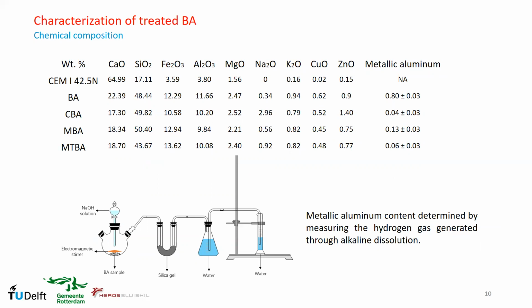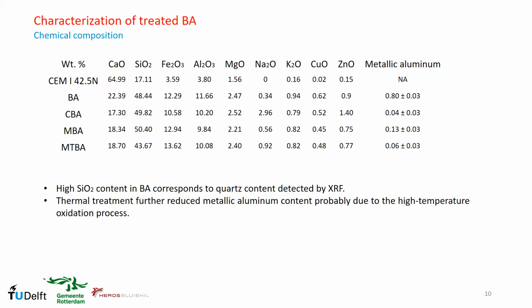Next, the chemical composition of the treated bottom ash by XRF. Here we see that in all bottom ash samples, the calcium oxide content is much lower than in Portland cement, while the silicon oxide is much higher in bottom ash, which corresponds to the quartz peaks detected by XRD. The metallic aluminum content is determined by measuring the hydrogen gas generated through alkaline dissolution with the setup illustrated here. We found that thermal treatment further reduced the metallic aluminum content in MBA, probably due to the high temperature oxidation process.